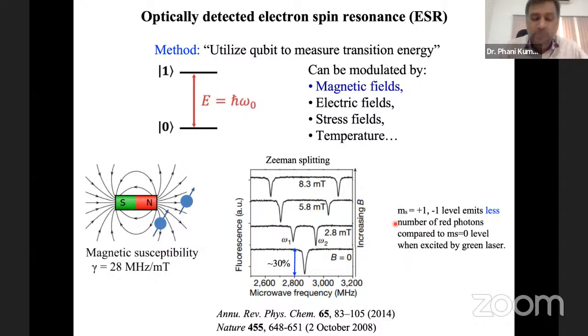Depending on the proximity of this NV center to the permanent magnet or to the magnetic fields, we see this Zeeman splitting. In this way we can perform magnetometry with these NV centers, and we know that the single electron magnetic susceptibility is around 28 megahertz per millitesla. So if you have 1 millitesla of magnetic field acting on the NV center, we have 56 megahertz splitting.